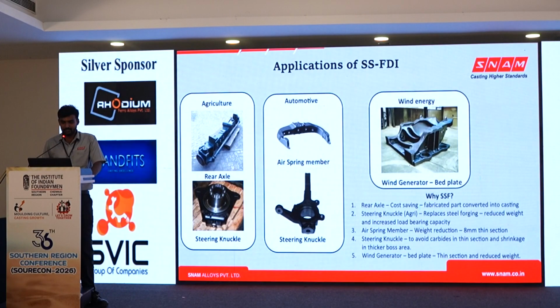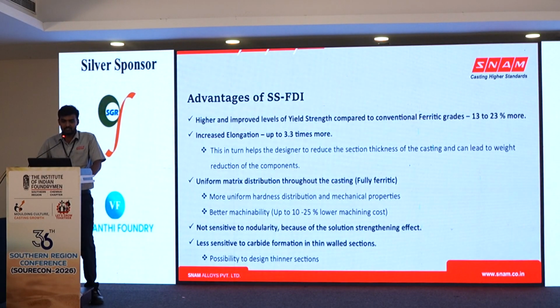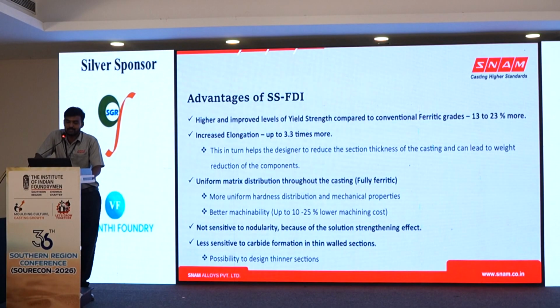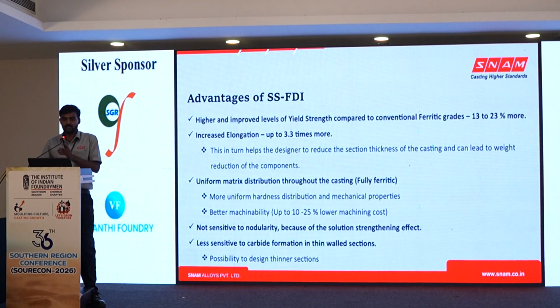because of ferrite matrix. Advantages of SS-FDI, as I discussed, it will increase the mechanical properties. We can see there is a 13 to 23% increase in yield strength and almost 3 times higher elongation, and it will have a uniform matrix distribution throughout the casting, and it's not sensitive to nodularity and carbide formation.